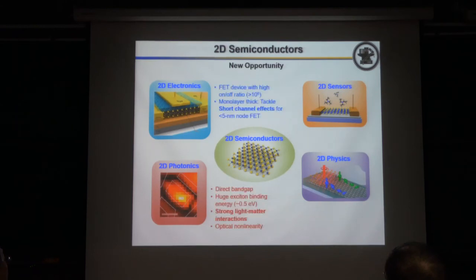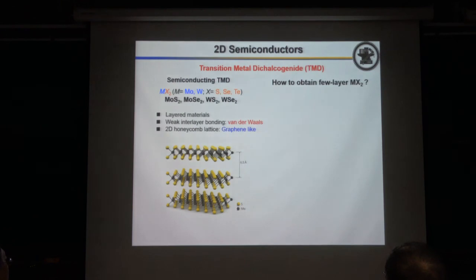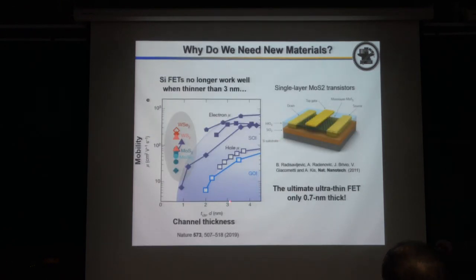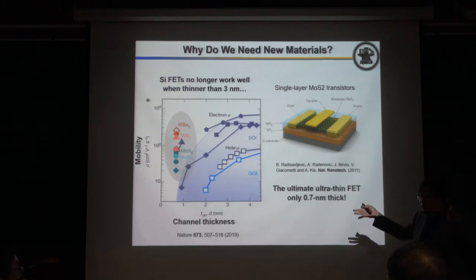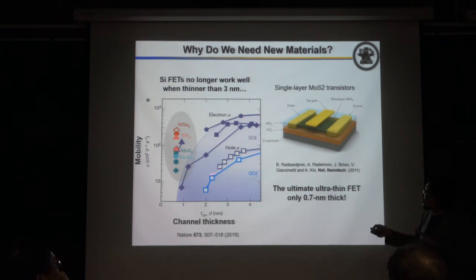This is the channel thickness, but when they say 3 nanometer it means the gate depth. The gate depth is not equal to the channel thickness. If you reduce the channel down to 3 nanometers thick, typically the gate has to be reduced even smaller, maybe 1 nanometer. So in the so-called 3 nanometer technology, the thickness is actually much thicker. If you still want to scale down, it will cause problems. So the 3 nanometer means the gate depth, not the thickness. It's a factor of 2 or 3 in this case.